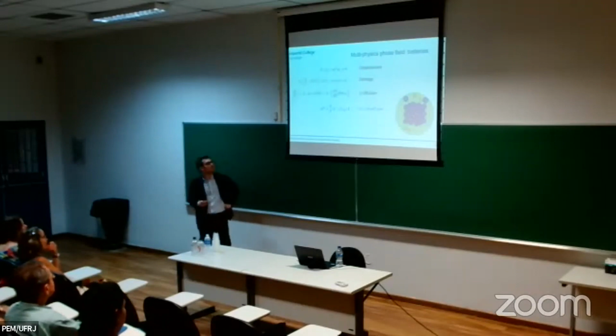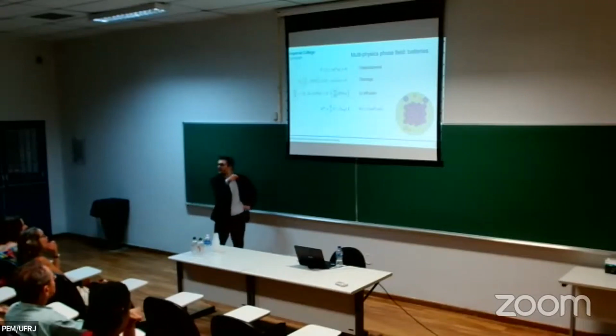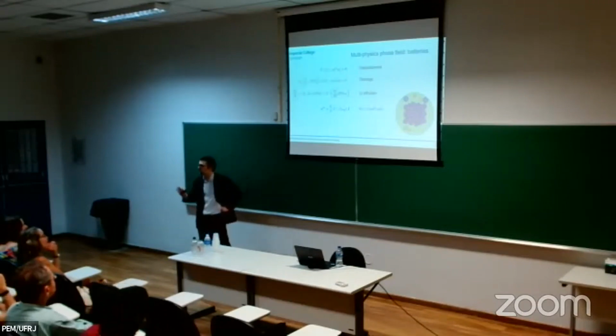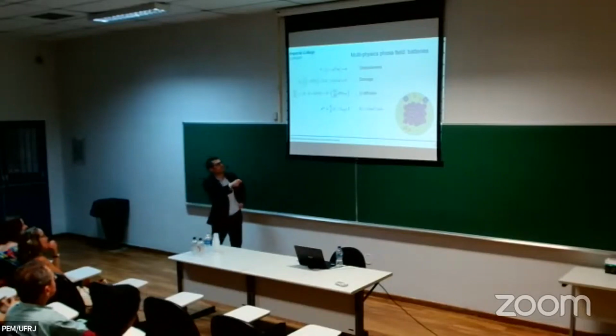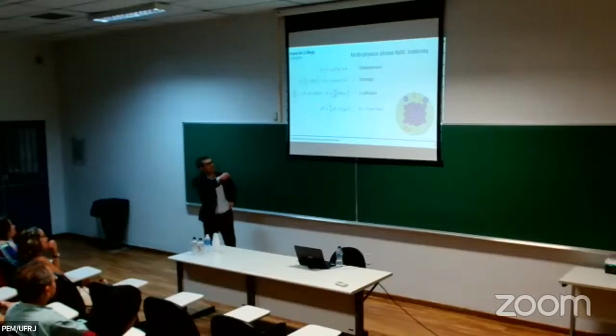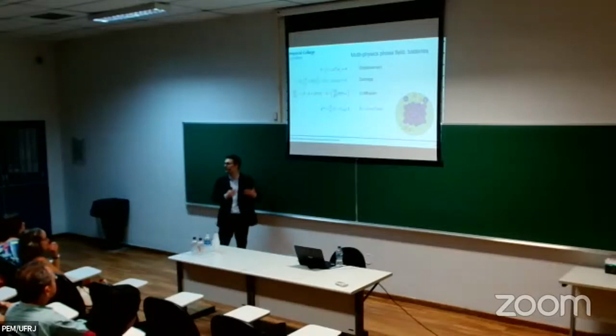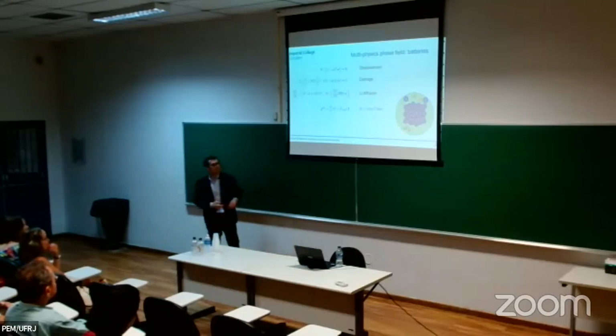There are two main differences. The first one is that it doesn't seem that the lithium changes the elastic properties a lot, in fact. And the second one is that we have these chemical strains that also exist in hydrogen, but they are very small, so we normally neglect them. But these are particularly significant in lithium, because the partial molar volume is quite high. And in fact, these chemical strains caused by differences in concentration of lithium, the swelling and shrinking of the particles, are what lead to the cracking process. We don't have any other mechanical load, it's just the lithiation process.